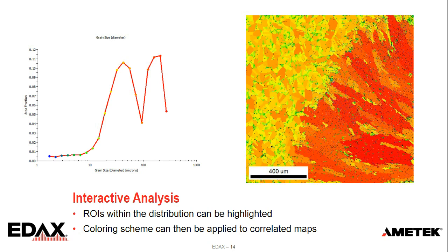So we see that there, and we can see that, sure enough, the weld grains are larger. They're red. The base metal is more in the middle range. The small grains are there, blue, but there's just fewer of them, and they're smaller, so they're harder to see.